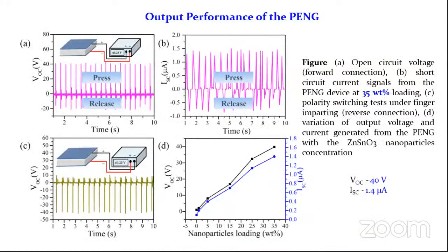So this is the output performance of the fabricated PENG. As you can see here, we have got a maximum output voltage of 40 volt and a maximum output current of 1.4 microampere. We measured in both forward and reverse connections. To check whether the signals are coming from the instrument or from the device, we went through the polarity switching test. We got exactly the same amount of voltage, but in opposite directions.